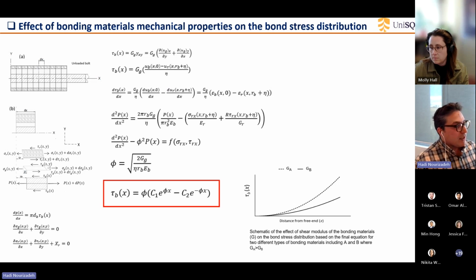In the literature, it is mainly said that the main factor affecting the bonding behavior of the reinforcing elements is the UCS of the grouting material. But by conducting some tests, we realized it is not the only factor that we should consider. We need to analyze more to see what exactly contributes more to this behavior. By developing some analytical models on fully grouted rock bolts, we realized that rather than compressive strength, shear stress or tensile stress, or for example elastic modulus or Poisson ratios of these grouting materials, the shear modulus of the materials is more effective.